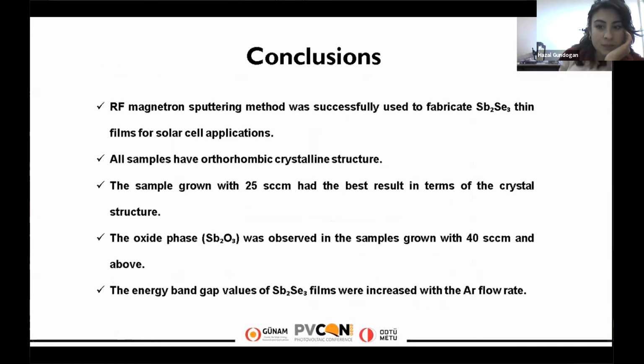So to conclude, in this study, RF magnetron sputtering method was successfully used to fabricate antimony selenide thin films for solar cell applications. All samples have orthorhombic crystalline structure. The sample grown with 25 SCCM had the best result in terms of the crystal structure. The oxide phase, antimony oxide, was observed in the samples grown with 40 SCCM and above.